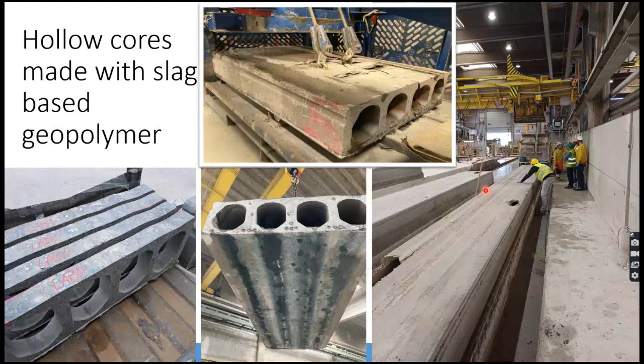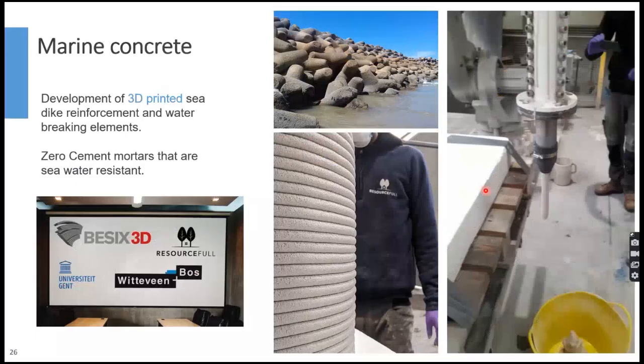This is a little bit more advanced pre-stressed concrete. Here we are doing the pilot trials, but this requires longer time towards implementation with these new kind of binders, because we have to study creep and creep relaxation, shrinkage, corrosion resistance of the cables. But of course you have to start the investigation now. By the time we can implement it, you start now to maybe implement it in 3 to 5 years.